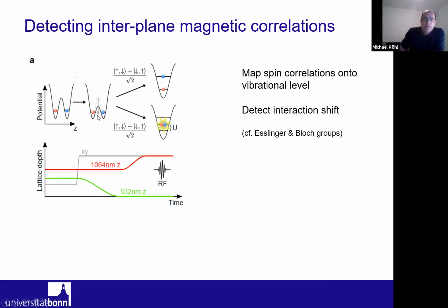And you do this by ramping the barrier in the double well appropriately. And then the singlet state will map into two spins in different vibrational layers of the lattice. And the triplet will map onto two spins in the same vibrational layer. And this is then offset, of course, by the interaction energy. So this is a technique that we apply to the two layers of our bilayer model.